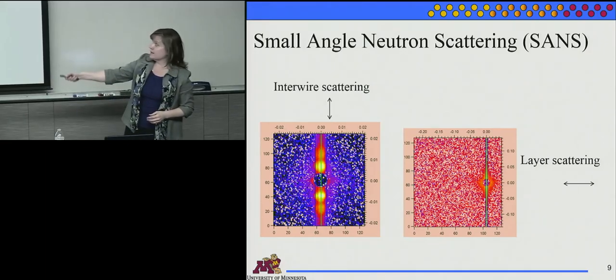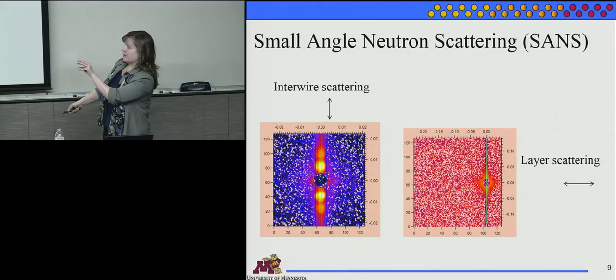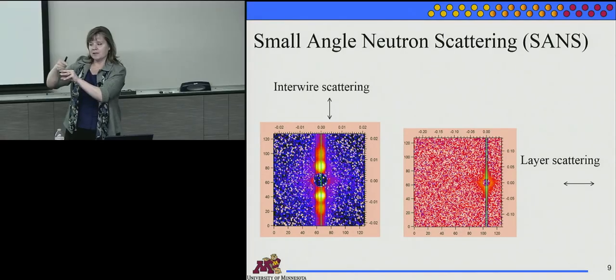So here you can see the samples now are in this direction, and the neutrons are coming at them and then scattering onto the detectors that you're seeing here. So the scattering in this direction is from the interwire diffraction, basically, scattering. And if you can go in this direction, you actually get, is there any layer to layer? Because your nanowires have layers, pancakes inside of them.